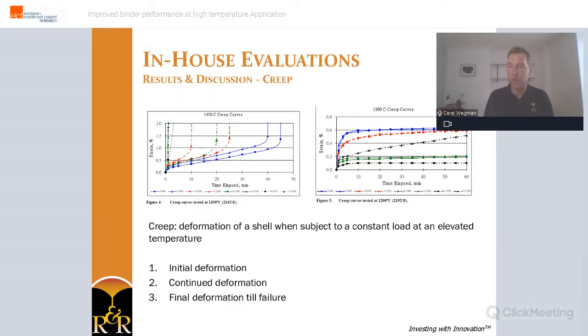Creep resistance of a shell is important, not only to avoid delayed leakage, but also to assure the casting its dimensional accuracy. Creep resistance is even more critical for direct solidification or single crystal casting foundries, because during the extended solidification process, the shell is subject to the molten metal pressure at elevated temperatures.